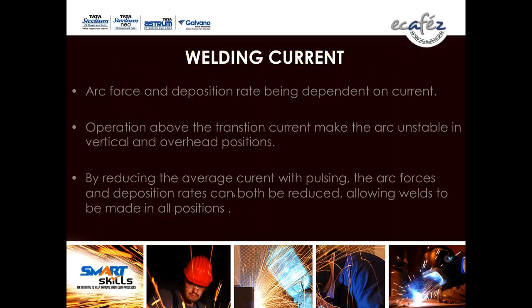Welding current, arc force, and deposition rate are dependent on current. Operation above the transition current makes the arc unstable. Please check your current. In the MIG process, there is a transition current, a transition range. Don't go excessively above the maximum of the transition range, or your arc will be unstable in vertical and overhead positions. By reducing the average current with pulsing, the arc forces and deposition rates can both be reduced, allowing welds to be made in all positions.